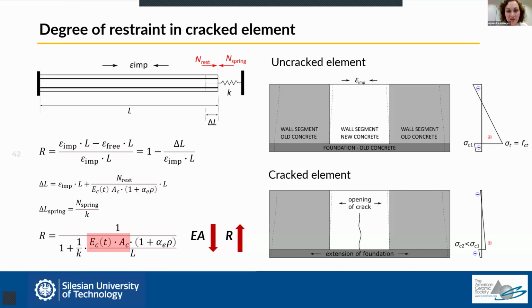Once the crack is formed in the wall, the stresses in the element decrease. This is what we would expect, which is on one hand really nice for the wall, but we should remember that the stresses will consequently also decrease in the foundation, which means we'll have less compression. If there is less compression in the foundation, the foundation will extend and pull the wall, consequently opening the crack. So again, lower stresses in the wall may not necessarily mean that the crack will be